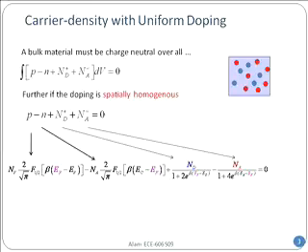One quick thing I want to point out: why is there a Fermi-Dirac integral on one side, and on the other side just a Fermi-Dirac function? Because in one case, I had continuum states, so I integrated over them, because I wanted to see how they are all occupied. For the donors and acceptors, I assumed a single level, so I didn't do any integral. Therefore, on the two sides, I have slightly different functions. That's no rocket science.